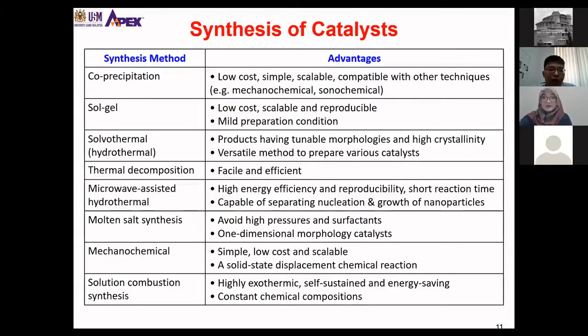Right. On the other hand, if you look at sol-gel method or hydrothermal method, they are better in terms of controlling the morphology of the catalyst. So morphology is important because it will determine whether your catalyst will have good surface area, better functionality, or so on. Okay. So sol-gel is also a very popular approach in the sense that it's low cost, scalable, and reproducible. And sometimes people use this sol-gel to do coating. Right? So we will see later on how we can use sol-gel method to do some coating on ceramic membrane and use it as a bifunctional ceramic membrane.